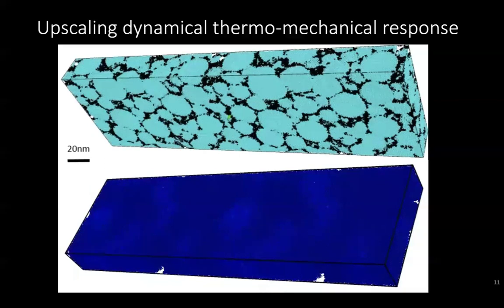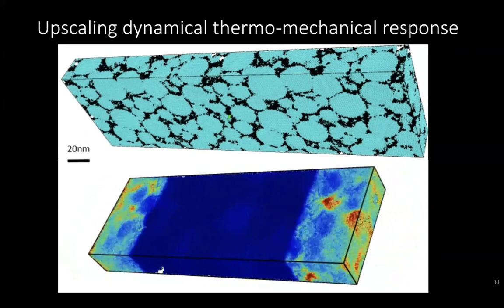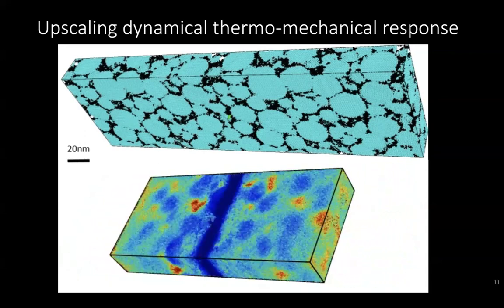And so these materials are plastic bonded molecular crystals. So each of these cyan color, that's a molecular crystal, and has a polymer binder, and you have this polycrystal composite. That's what the real materials look like. And if you take one of these materials and shock it, this is a 30 million atom simulation, you create not one hotspot, you create a family of hotspots and a distribution of temperature that originate not just from one pore, but lots of little pores, pores that have different shapes, they're oriented at different directions.